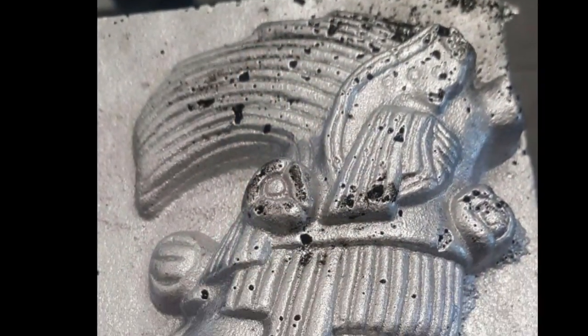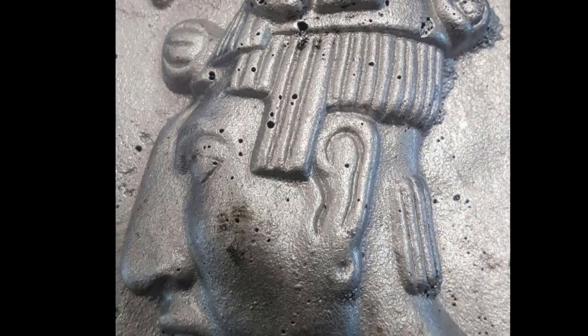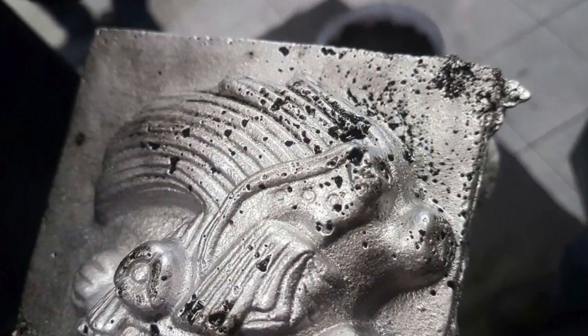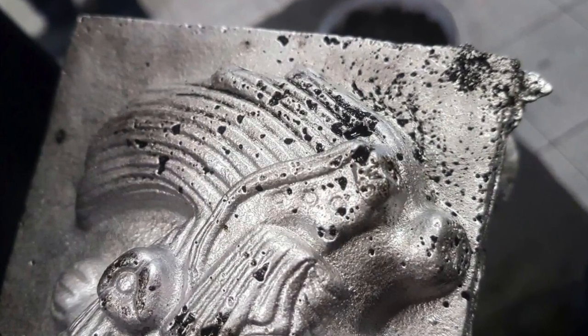The most common defect in our piece was gas porosity, perhaps caused by bubbles of gas trapped within a casting during solidification. Degassing in aluminium is the removal of hydrogen dissolved in the molten aluminium. It is necessary to degas the molten aluminium because the solubility of gaseous hydrogen is 44 times greater in molten aluminium than in solid aluminium. This causes an excess release of hydrogen during solidification, which eventually leads to porosity defects throughout the casting.